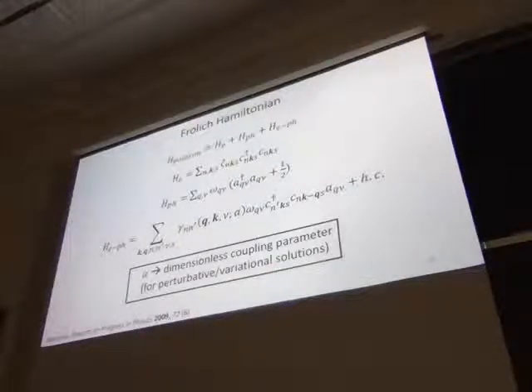And so the on-site energies correspond to summing up all your electronic energy. N is your band index, K is your momentum, and S is your spin. So you just create a state with a certain energy value. Same thing with your phonons: you have your phonon momentum and band index, and it has a certain energy and occupation. And then your cross term is just the matrix element of the cross term, so you have an electronic state interacting with the phonon state.